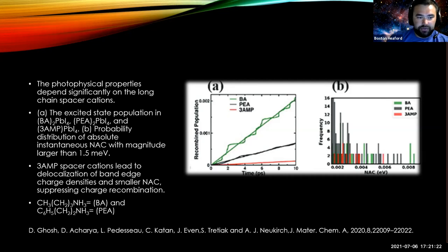And so those are the ones looked at, and it shows the excited state probability distribution and the absolute instantaneous non-adiabatic coupling with magnitude larger than 1.5 millielectron volts on these graphs. And so the 3-AMP spacer cations tend to lead to delocalization of the band edge charge densities and smaller non-adiabatic coupling, which suppresses the charge recombination, which again is good. That one seems to be a leading contender as a spacer cation in the 2D perovskite systems.